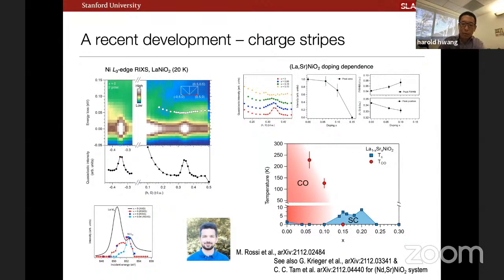And it's interesting, because the stripes here do look quite distinct from those seen in, say, the 214, or as I'll come to, other layered nickelate compounds, where those are these diagonal stripes, right? Shown by electron microscopy and neutron scattering and other techniques, like at Brookhaven. And so this is oriented in the high symmetry 1,0 direction, and it doesn't apparently disperse very much as a function of doping until we lose visibility as we enter the superconducting dome.